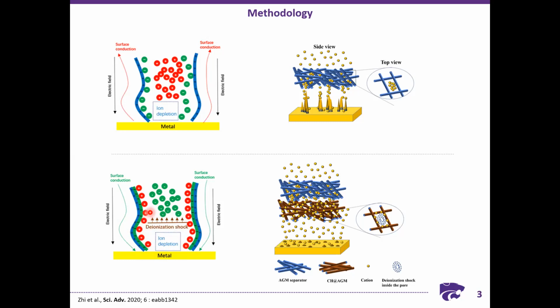So because of that, the oppositely charged species, which are the lithium or zinc cations, can be conducted not in the bulk solution but along the surface of the fibers, along the surface of the negatively charged fibers. This is called surface conduction.